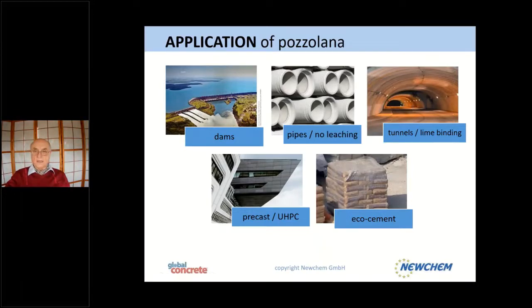The same thing applies to lime binding. We have now done shotcretes in Austria where we could reduce the free lime, which is washed into these drainage pipes, by about 2/3, which means that you can reduce a lot of your maintenance cost of the tunnels. By the way, we want at least a 100 years working life, which is easily done if you have no leaching. We have a lot of customers making precast and ultra-high performance concrete because more binder naturally gives a better mechanical strength. And we are working a bit on the eco cements, trying to reduce the CO2 and improve the quality of the cement.